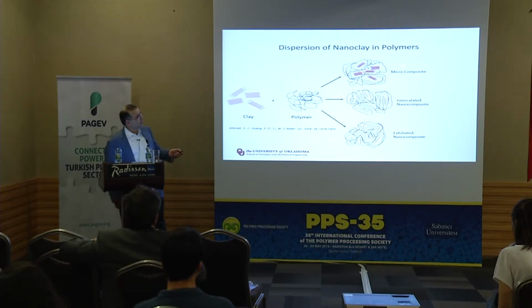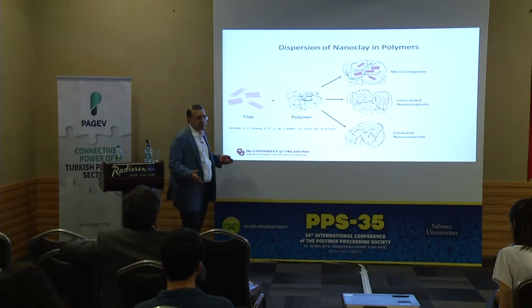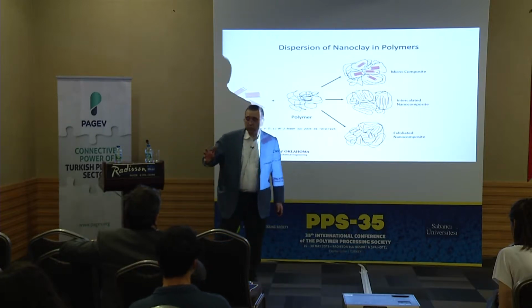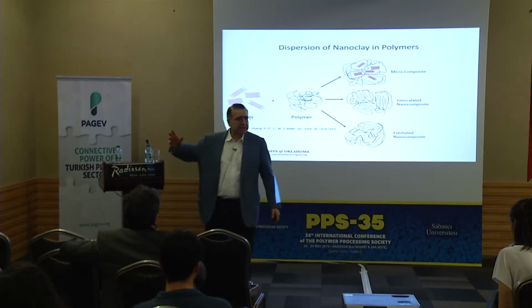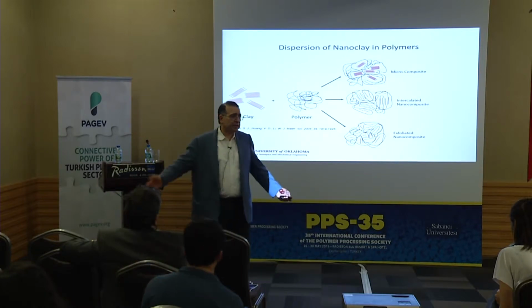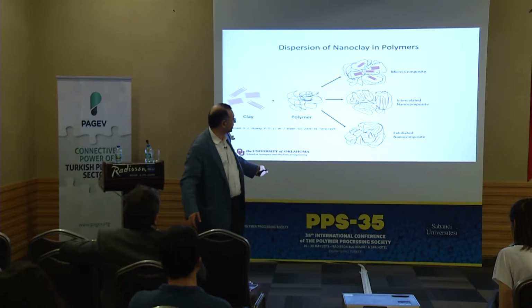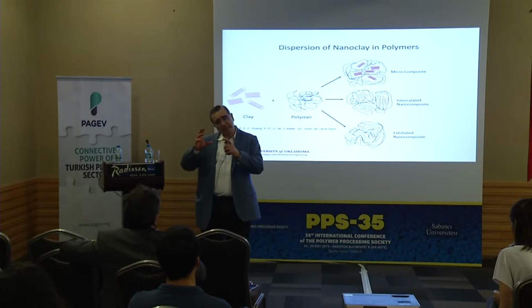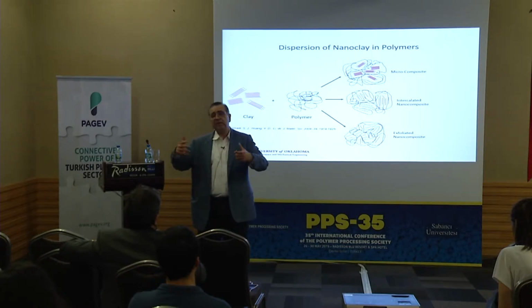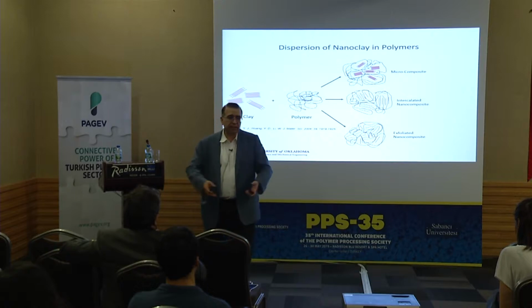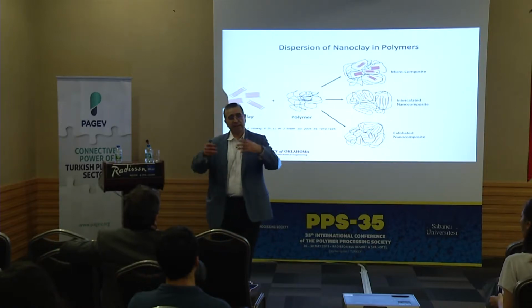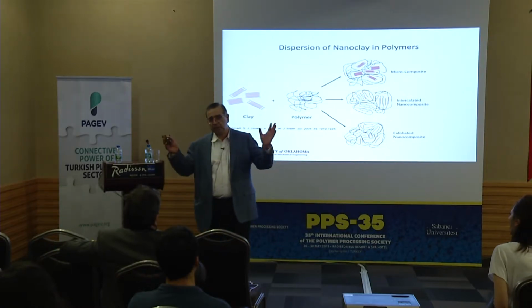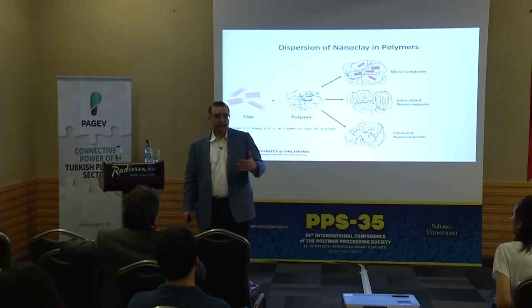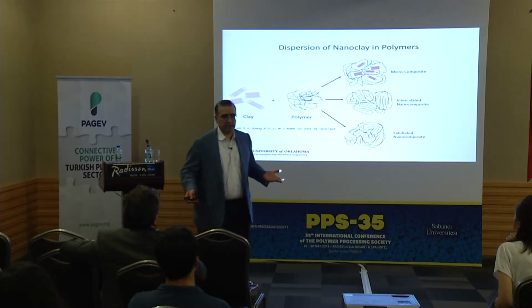And if you have these microclusters, how big are they? Maybe they are 5 micron, 10 micron, 20 micron. It can be as large as 50 micron. Then you are not really getting any benefit from the regions where you have exfoliation. Your big clay clusters will govern the behavior. They will essentially accumulate the stress. They will absorb moisture. They will give you everything that you do not need. And then you will say, well, it doesn't work for us, right? So it is kind of difficult to get rid of these large clusters.